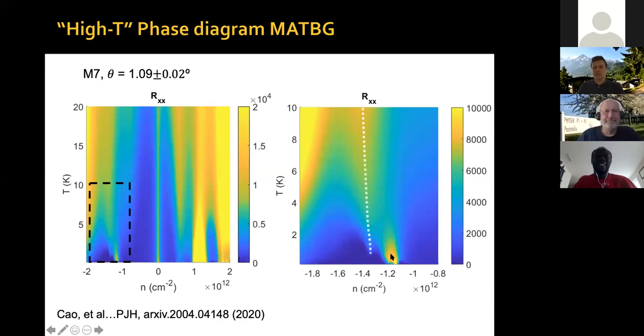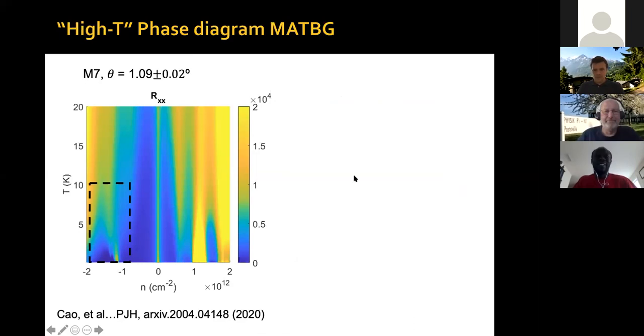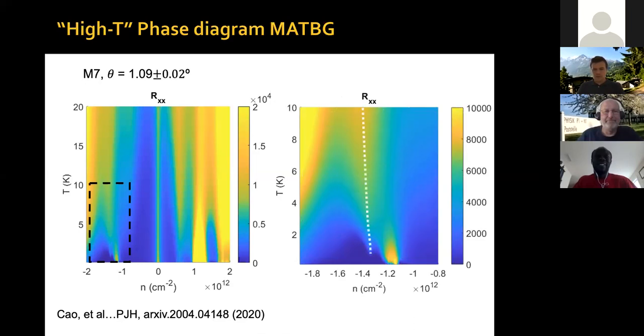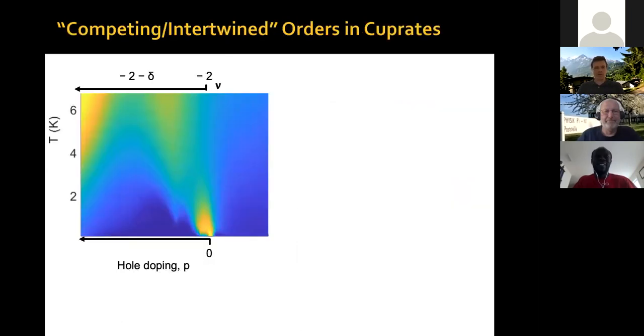And now you can see that there is some feature that comes from relatively high temperature. We sometimes call it the banana, because in this color scheme it looks like this yellow, a little bit bent thing. That feature goes down and seems to create a depletion in the superconducting dome, which is this dark blue region. Again, let me zoom in a bit more.